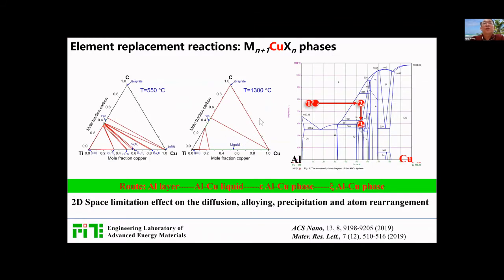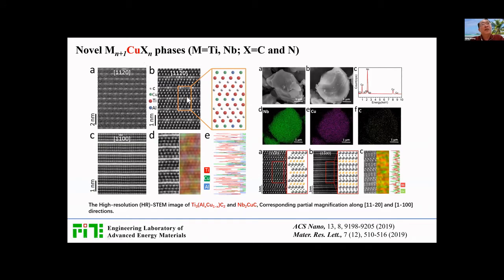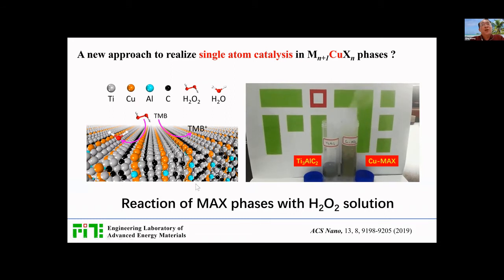Here I show an example of making a replacement with copper atoms. We can see from the phase diagram calculations that the copper ternary MAX phase has no way to exist, because the competing phases of these alloys are much more competitive. But if we use the same strategy to make a replacement between the copper atoms and the aluminum, we can finally synthesize these new MAX phases containing copper in the A layer. And I think these new phases may show some new properties.